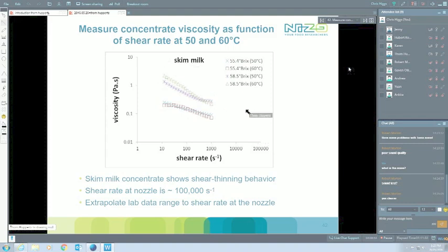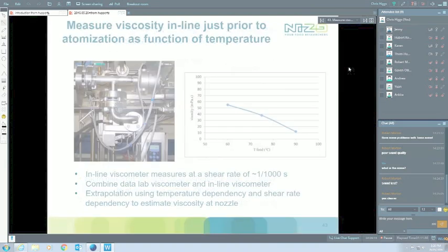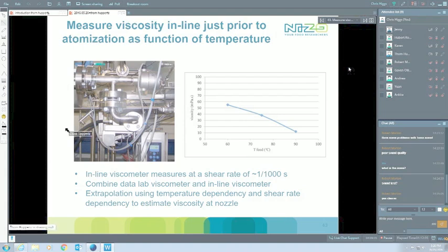So we need to extrapolate those data to get a good idea, and you basically see your viscosity will be dropping another order of magnitude by that point. That we need to know. The other thing is, of course, what is our effective temperature? In the lab, we can measure at 50 degrees, we can measure at 60 degrees, no problem. Given the time scales of the measurements, we cannot really measure any higher, because other changes would be happening and the sample might be thickening because of the long time scales there.